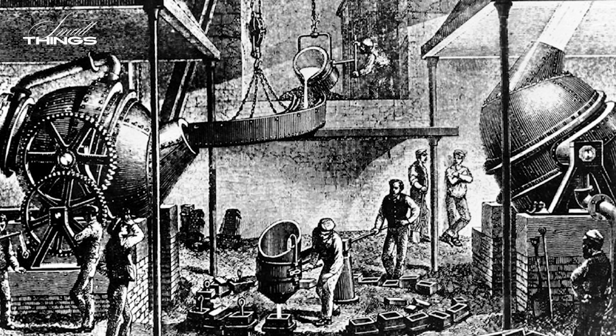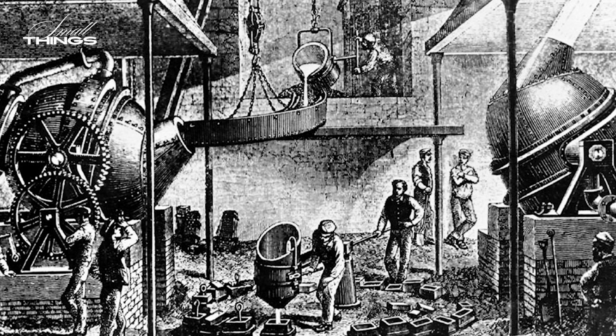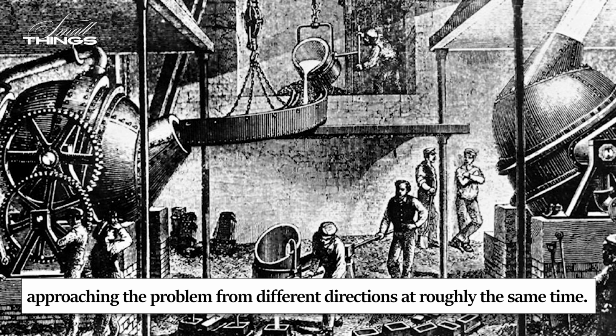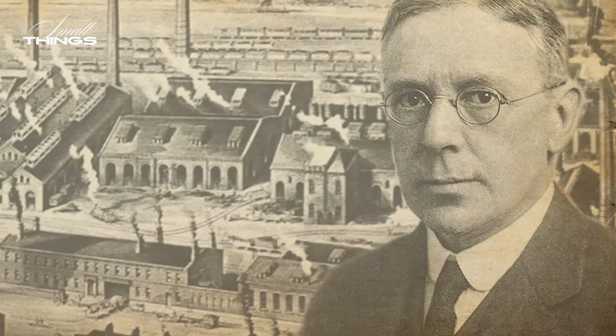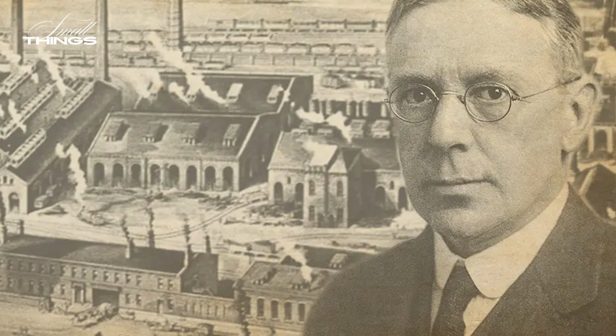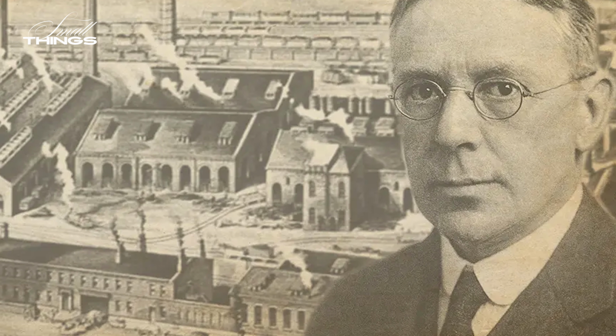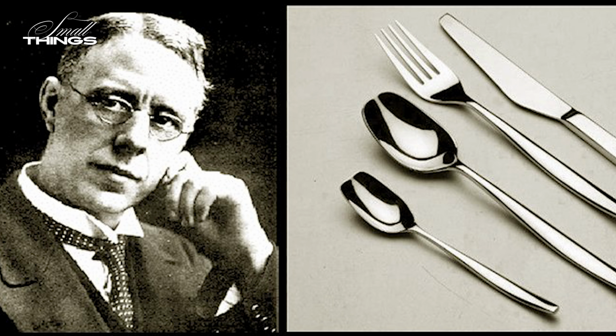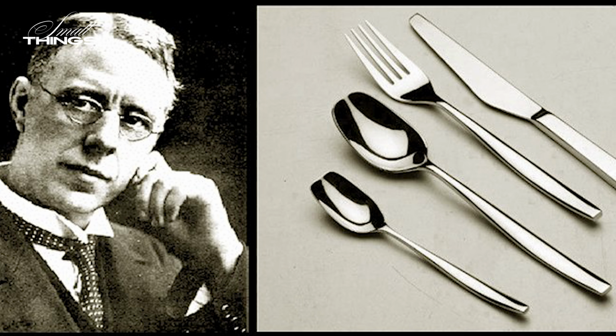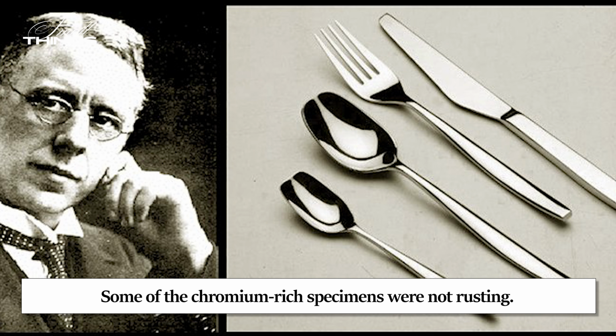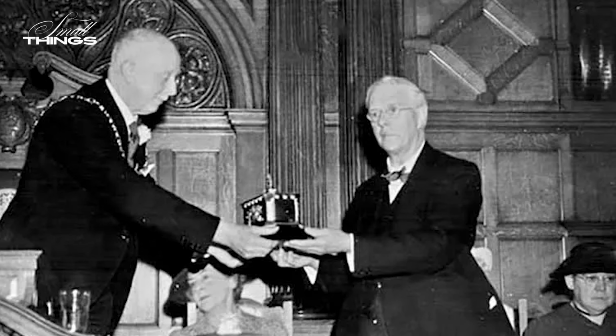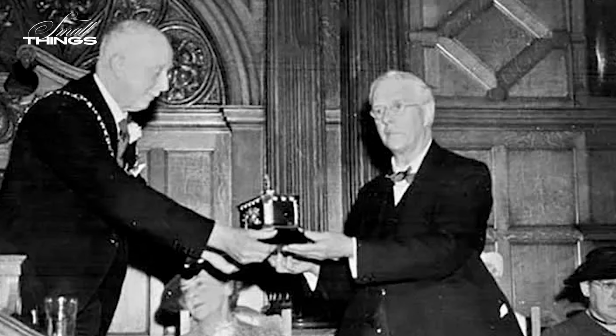Metallurgists across Europe and America were searching for a corrosion-resistant steel, approaching the problem from different directions at roughly the same time. In Sheffield, England, a metallurgist named Harry Brearley was working on a different problem, developing a steel alloy with better resistance to erosion from the heat of rifle barrels. In 1913, he began testing alloys with different chromium contents. Most failed to solve the erosion problem. But while reviewing and discarding rejected samples, he noticed something unexpected. Some of the chromium-rich specimens were not rusting. Weeks after being left in the laboratory, they remained clean and bright while other samples had turned orange.